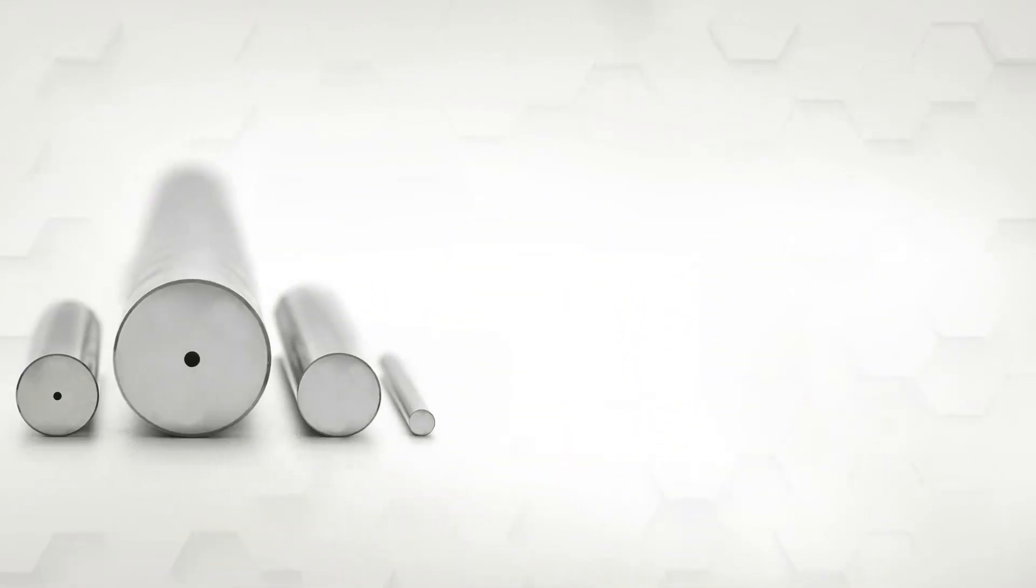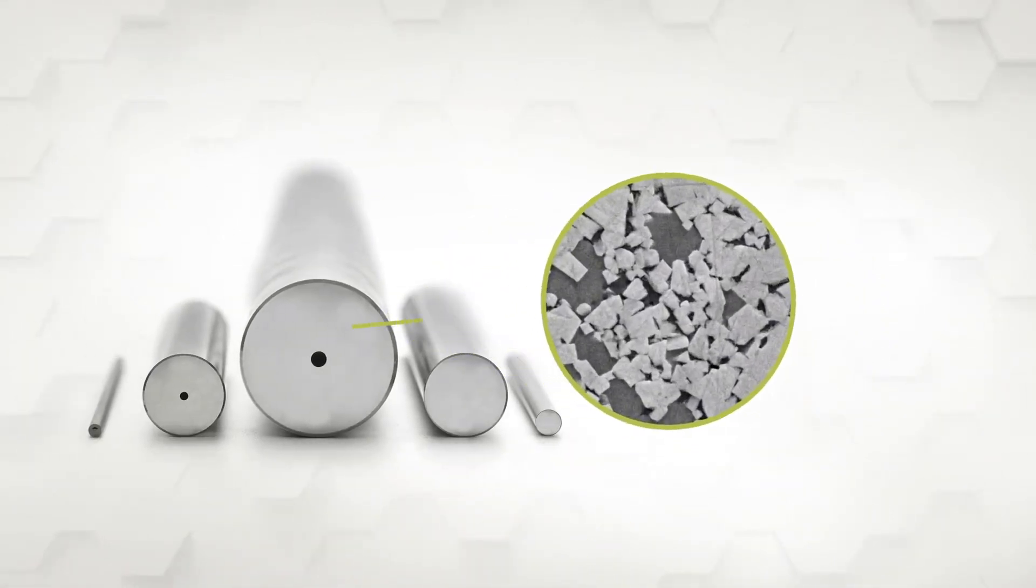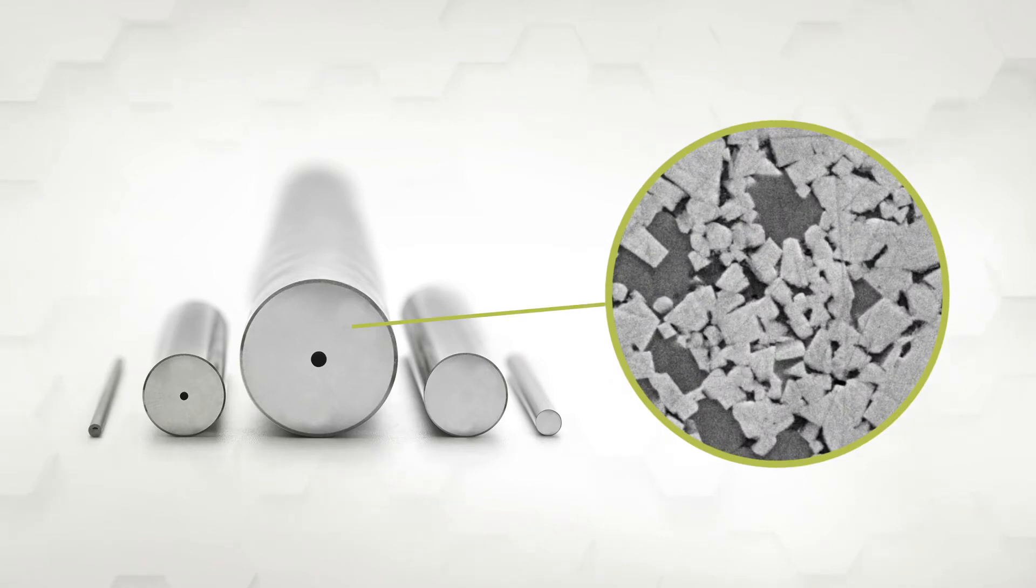Generally, the frequency of cleavage fractures increases with increased grain size, while the amount of shear fractures increases with increased binder content. The most frequent type of fracture seen in cemented carbide is from the crack path through the binder.